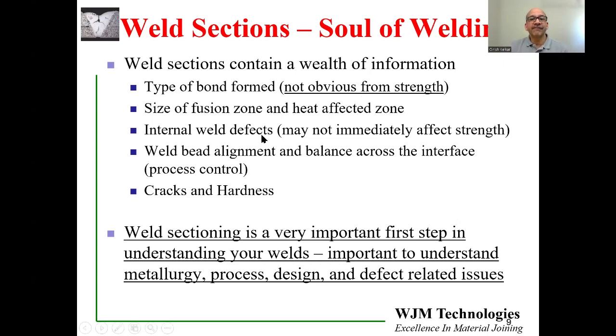We can also see internal weld defects, again, which may not be obvious from the weld strength testing. So there might be some fine defects, such as fine cracks or porosities or undercut on the edge of the weld, which may not be very obvious in initial mechanical testing, but will affect the life of the weld. We can also see weld bead alignment, whether the nugget or the heat affected zone is symmetrical or is it biased on one side, and that can tell you issues related to process control. And then, of course, cracks and hardness, which affects the life of the weld.